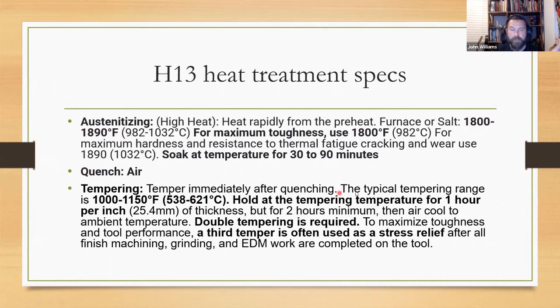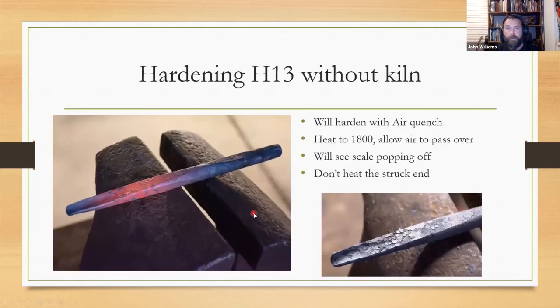And tempering, this is another thing that I want to point out, is that technically you should be tempering at 1000 to 1150 and hold for an hour per inch. Well, you're not going to do that in the oven that you bake cookies in, right? So hardening H13 without a kiln. Now I have a kiln, so I can anneal this. So I have a struck end because I can do that, but you don't want to ever heat this whole area up. Okay. And what are the particulars here?